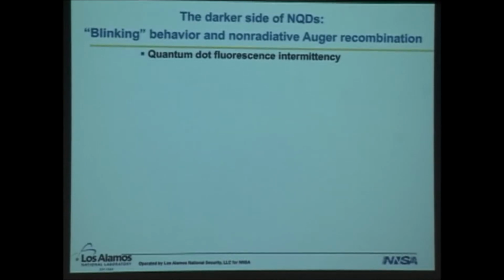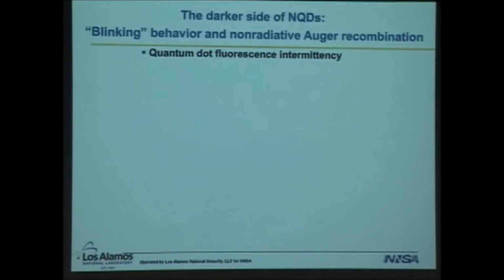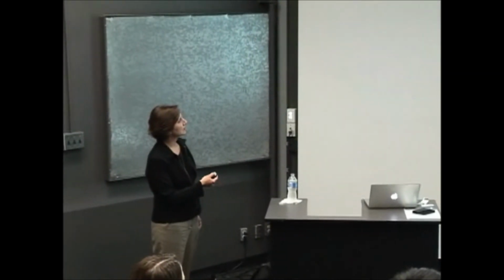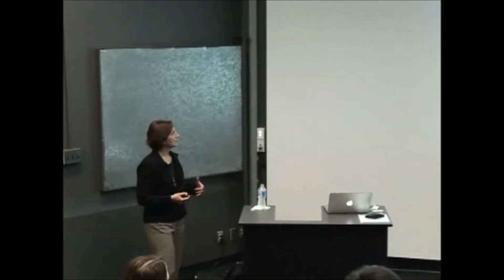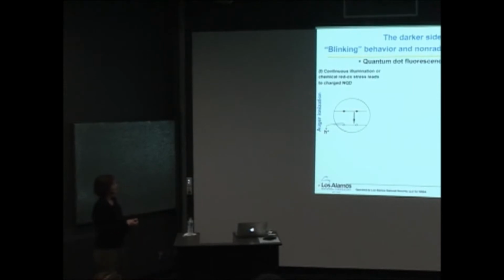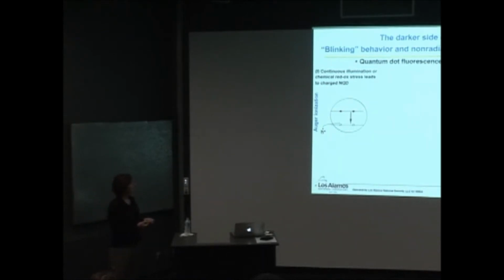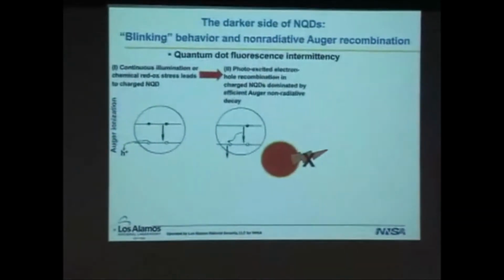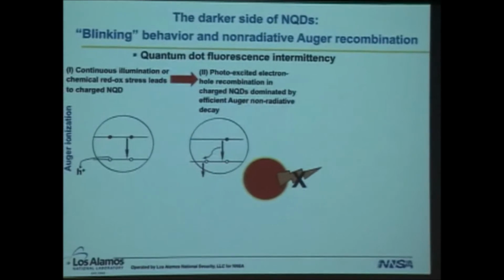In addition, quantum dots are characterized by very efficient non-radiative Auger recombination. And so I'll explain a little bit more about that in a moment. But in terms of fluorescence intermittency or blinking, under continuous illumination, it is thought that the quantum dot can become charged. This can also happen in particular chemical environments, redox active environments. And so it can be due to an Auger ionization process or other processes, but nevertheless, the quantum dot becomes charged, and then the charged quantum dot is susceptible to Auger recombination. So what we have now is an extra carrier, if you will.